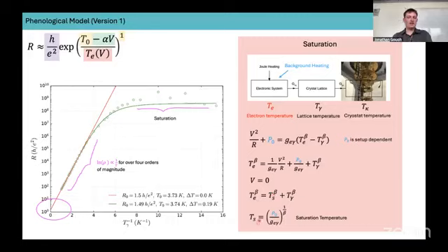The saturation temperature increases with this background heating power, which is an umbrella term to include all sources of heating in the experimental system. And it also increases as your electron-phonon coupling strength, this G term, decreases. This has also been verified by experiments, as samples with a weaker electron-phonon coupling, say graphene, saturate at much higher temperatures than the indium antimonide that I look at.